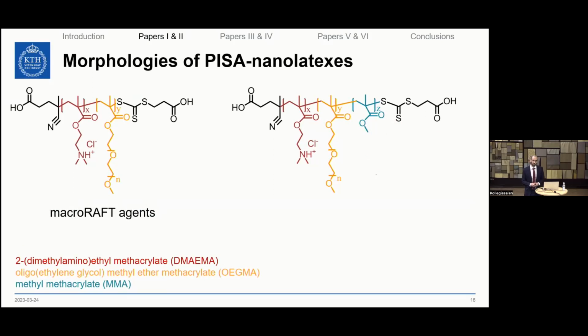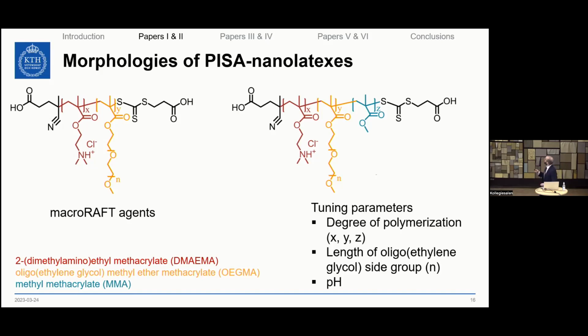Focusing on the morphologies of PISA nanolatexes, we have prepared macro-RAFT agents which are comprised of protonated PDMAEMA and long hydrophilic OEGMA units. And we have chain extended them in water with MMA in order for the hydrophobic block to prepare these nanolatexes. And this system has enabled us to study the degree of polymerization of each block, the length of the oligoethylene glycol side group, as well as the pH of the dispersion and how these parameters relate to the final morphology that we can obtain.